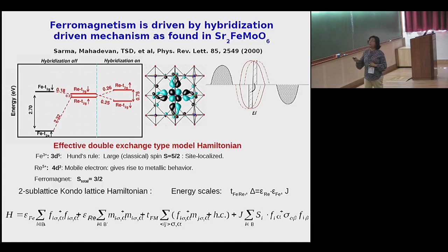And this, being completely determined by the hybridization, can actually support a very high transition temperature. At a model level, you can think of it like an effective two-site double exchange type model, where you have a large core spin sitting at the iron site, and this core spin interacts with the itinerant spin in a way that strongly favors one particular spin orientation of the itinerant spin. And this itinerant spin is basically delocalized over the iron-rhenium sublattice. So you can write a two-site double exchange like model to explain its magnetism.